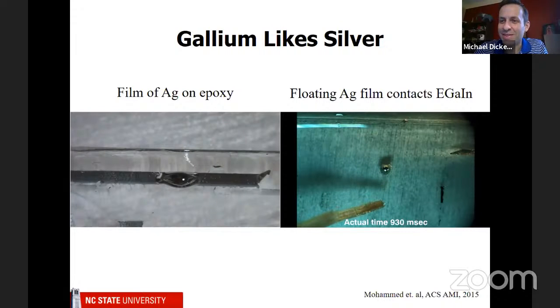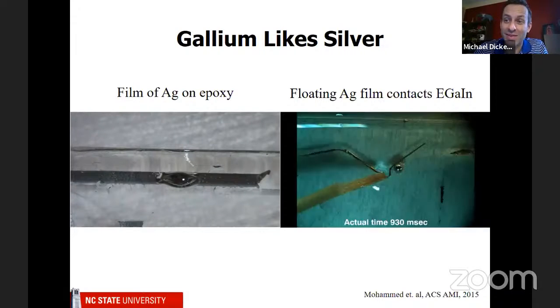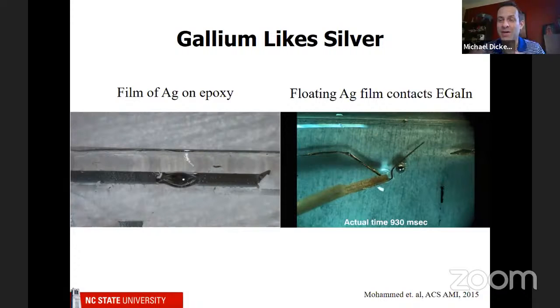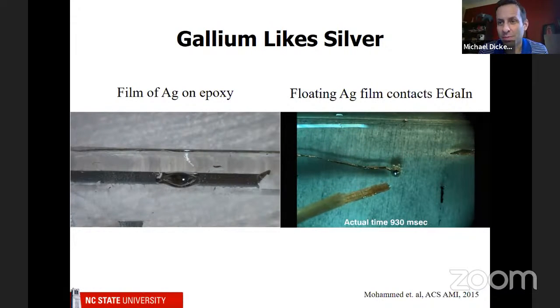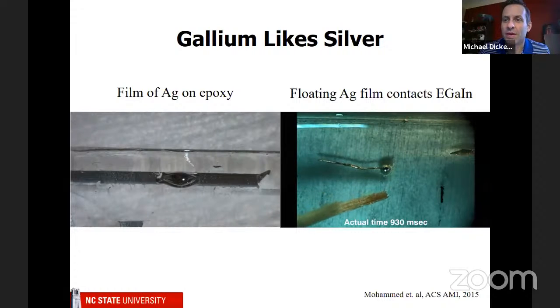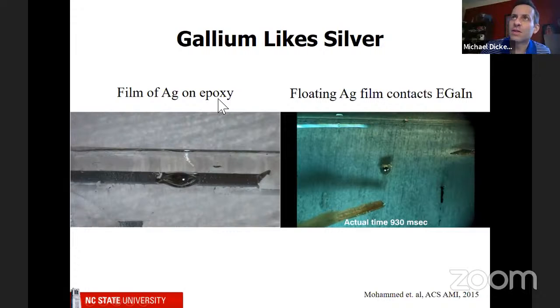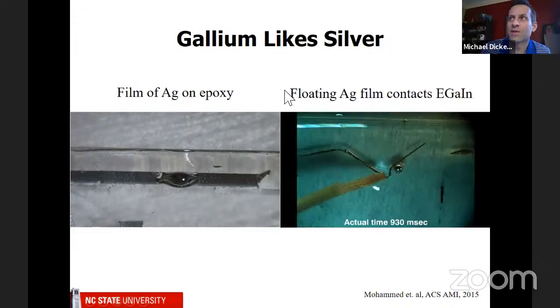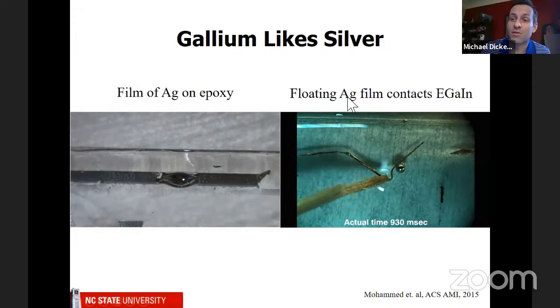And it's because the gallium likes to wet the silver, so it's trying to maximize the amount of contact area it has with the silver. It probably dissolves some of the silver and eventually it becomes saturated. All right, so there's two extremes here. On the left, the silver is glued to the surface. Over here, the silver is floating.